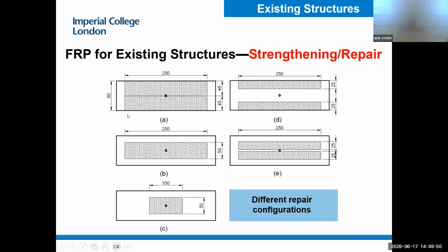We attach FRP on the steel plate with different configurations because we want to investigate how the bonding length, bonding width, and location of the FRP material affect the performance of the steel plate. And in the fatigue test, we want to get this crack propagation curve.